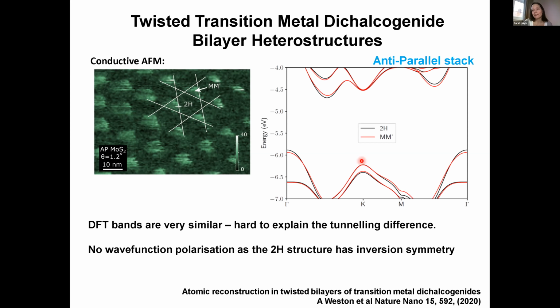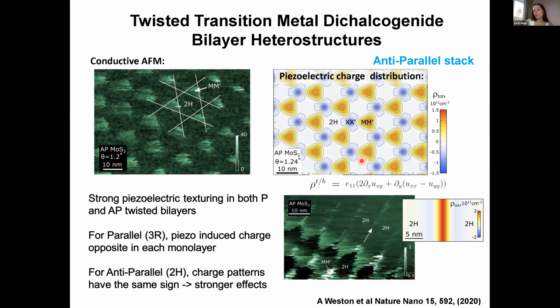And the 2H structure has an inversion symmetry, so there isn't a difference between the different 2H type domains. And so, as I say, the theorists then went back to the drawing board and looked at the fact that here we're getting a piezoelectric charge distribution, which is again being visualized in this conductive atomic force microscopy. We don't see that in the 3R type domains, and that's due to the fact that here we've got differences in the way that these two behave.